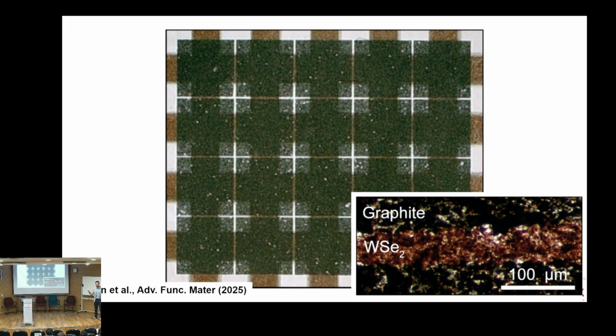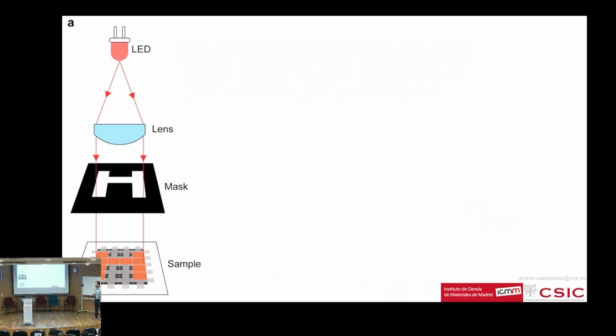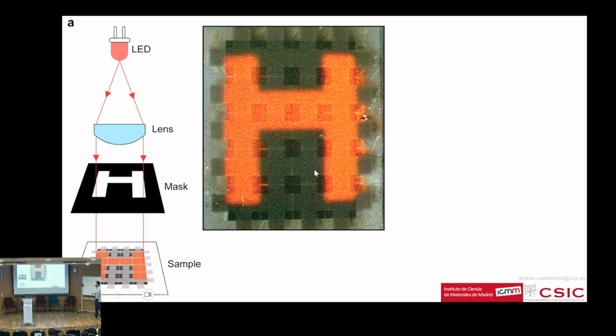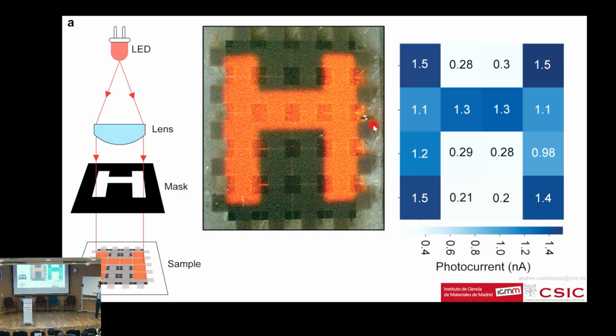So lithography-free, no metallization, no nothing. No ultra-high vacuum, no even high vacuum, okay? So now let's see if it works as a camera. We take a mask with a pattern, an LED, we illuminate it on top of the device, and when we measure the photocurrent of the different pixels, we see that indeed we are able to reproduce the illumination that we are projecting on our device. So we managed to do a 4x4 image sensor in the lab, which, okay, sounds not very exciting, but it's the first time. I've been working on optoelectronics for many years. This is the first time that I actually did a real image sensor, okay?